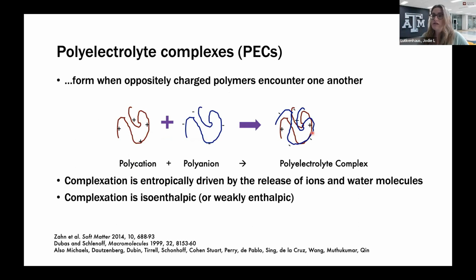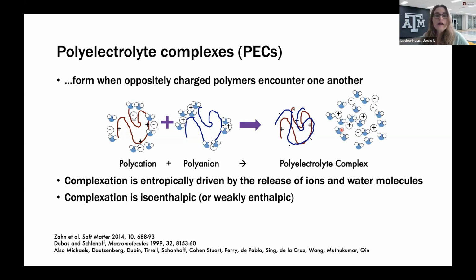Electrostatic interactions really do help drive complexation, but it's entropy that is the major contributor. This is because when the two polymers come together, these small counter ions are released into the external solution, and there's a huge entropic gain associated with that. Not only that, there's also a release of those hydrating water molecules. So the water molecules that were hydrating the polymer also get released. Some of them get released out into the external solution, further increasing the entropy.